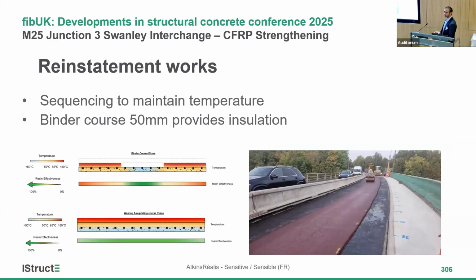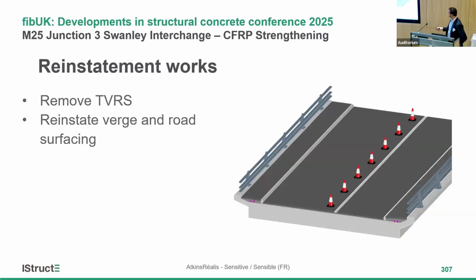For this case, we come for sequence application of the binder course, as we saw in the trials and experiment section, where only the central strip was applied with the binder course, and then you wait for the temperature to reach the ambient temperature, and then the other 2 sides were applied with the binder course, whereas the wearing course was applied in a single go. Finally, remove all the TVRS, or temporary vehicle restraint solution system, then reinstate the verge and the road surfacing.